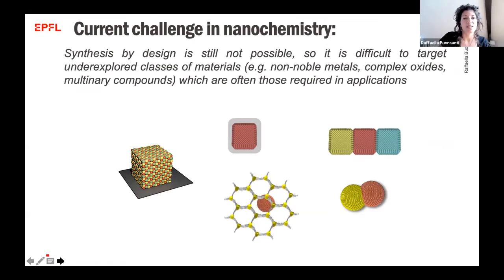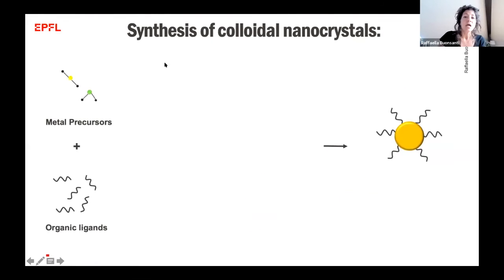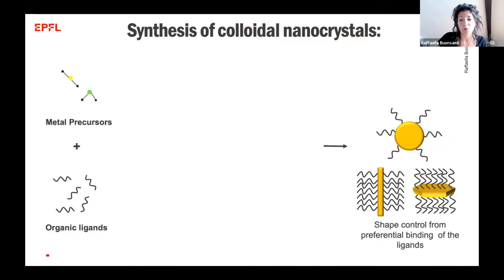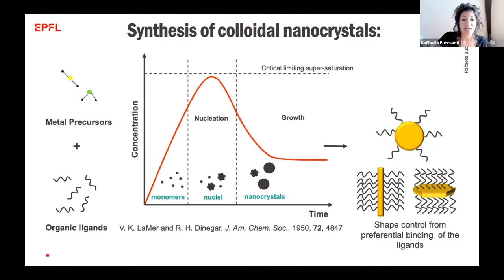Now, why is synthesis by design still challenging? What we know is that when we start in a flask with a metal precursor and organic ligands, we form nanocrystals, and the organic ligands help to control the shape by preferentially binding to certain crystal facets. And we are mostly still relying on the LaMer diagram, based on which the metal precursor and organic ligands somehow form monomers. Then when we reach the critical limiting supersaturation, nucleation occurs, and then eventually growth.